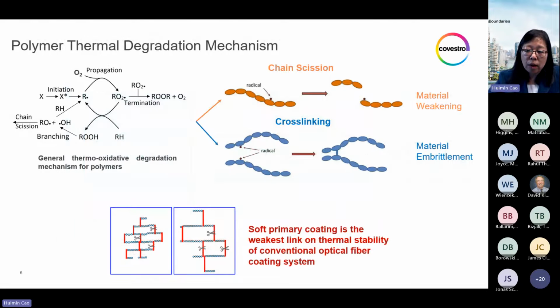Before we dive into how we designed our new coating system, it is important to understand the general polymer thermal degradation mechanism. At the high temperature range that's relevant to this specialty fiber application, at least higher than 100 degrees C, hydrolysis as a polymer degradation route is no longer that relevant because of the lack of moisture at those extremely high temperatures. So the main degradation mechanism is thermal oxidation, plus some thermal pyrolysis.